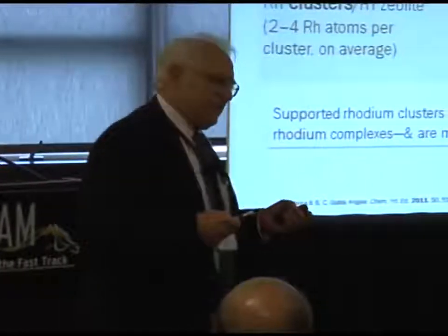This is going to be a mixture of some mononuclear species and clusters that are probably 2 to 4 atom clusters, but they're very small. And what we see is that the activity for conversion of the ethylene goes up substantially, and the selectivity for dimers drops way down. We've put in neighboring metal centers, we've put in the facility for hydrogen activation and dissociation, and we've made a better hydrogenation catalyst.